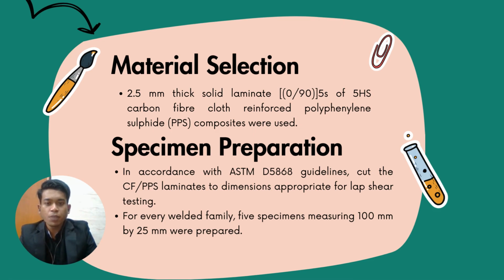Secondly, specimen preparation. In accordance with the ASTM D5868 guideline, cut the carbon fiber and polyphenylene sulfide laminate to the dimension appropriate for lap shear testing. For every weld family, 5 specimens measuring 100 mm by 25 mm were prepared.